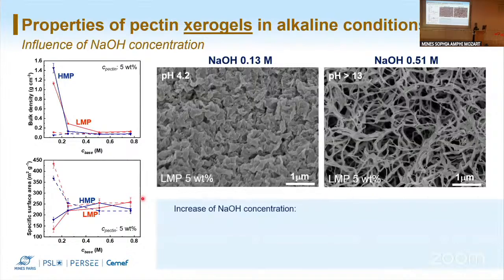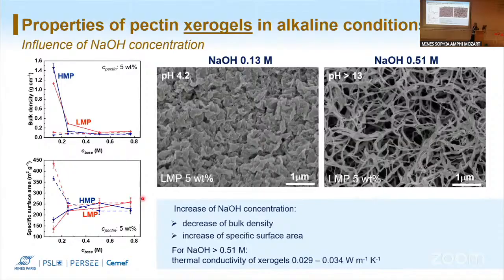So for the xerogel materials, when we increase the concentration of sodium hydroxide, we have a decrease of bulk density. We have an increase in specific surface area, and we tested the thermal conductivity of the materials that showed the best surface area and bulk density values, and we saw that it was between 0.03 to 0.035 watt per meter Kelvin, which is not super insulating, but it's very low still. It's in the level of the insulation materials that are used right now. Most importantly, the most important fact was that when we had a high concentration of base, we could obtain the same materials by evaporation as we could by supercritical drying.